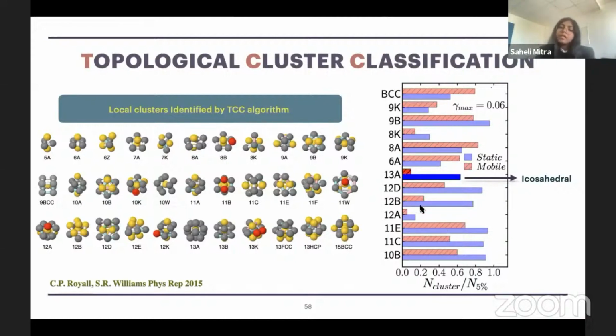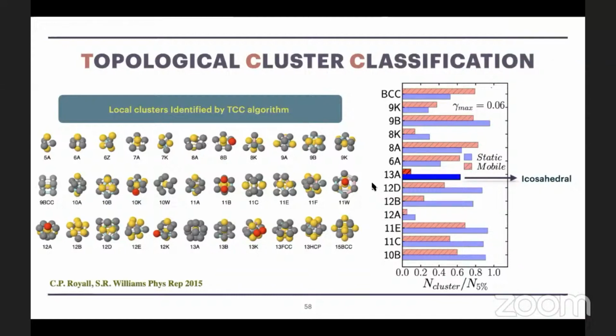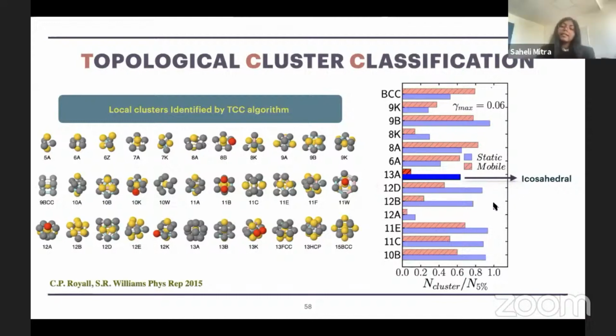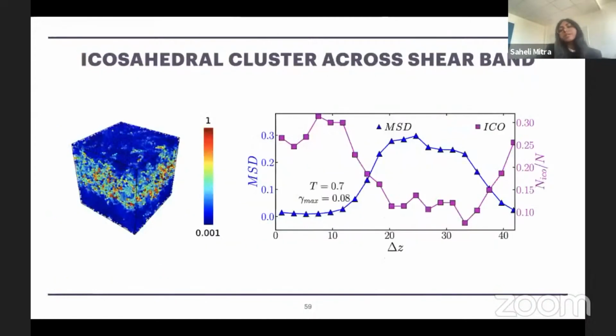For example, if we look into the 13A, which we have highlighted, 13A corresponds to icosahedral clustering. We see that static particles, for most of the cases, have high association with icosahedral clustering compared to the mobile particles. Since we have been talking about icosahedral clusters again and again, we want to see the cluster association to this particular cluster in the presence of a shear band.